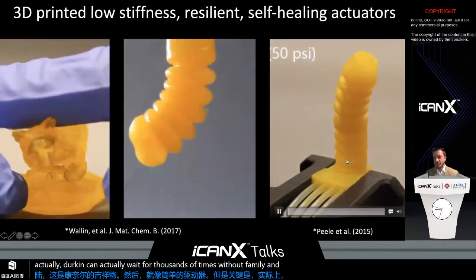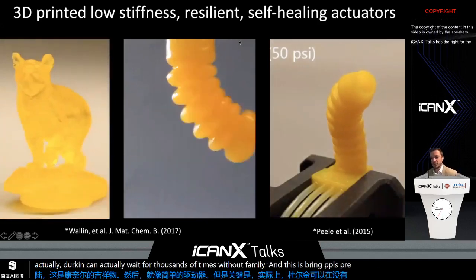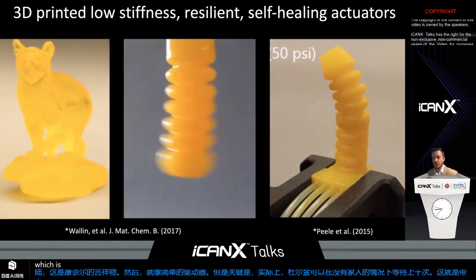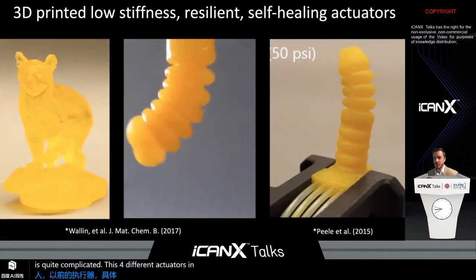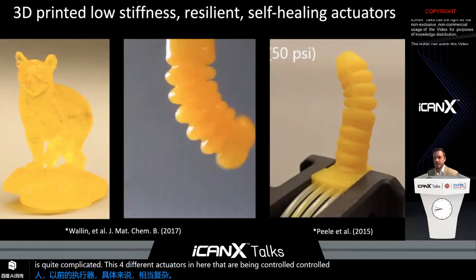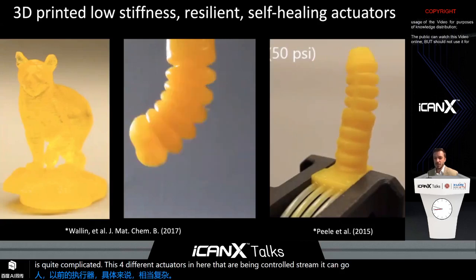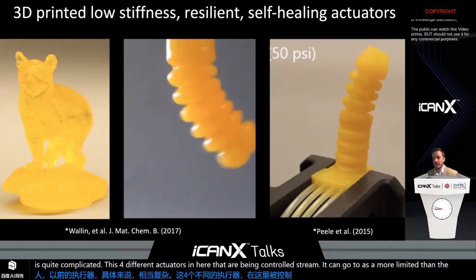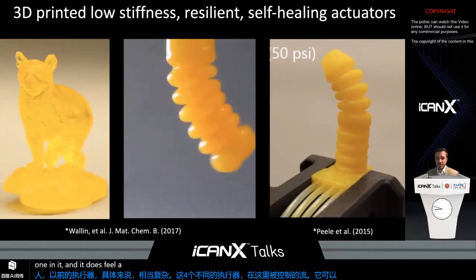And this is Brian Peel's previous actuator, which can print, which is quite complicated. There are 4 different actuators in here that are being controlled. But the strain it can go to is more limited than the silicone one, and it does fail after just tens of actuation cycles.